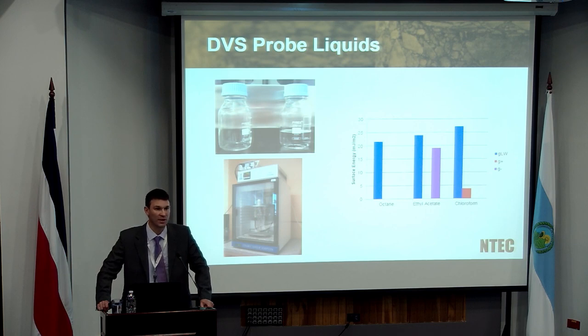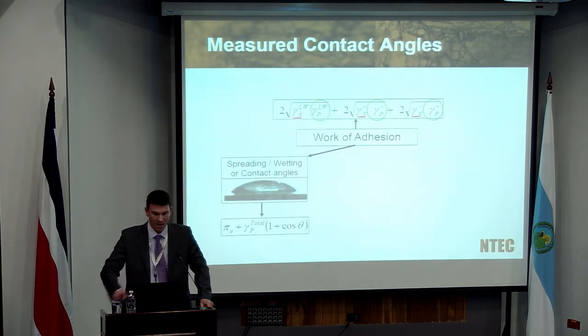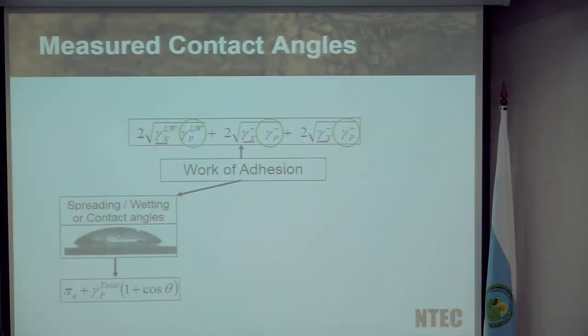How would we do it for the bitumen? Well, slightly different. Because now, although we're going to use exactly the same philosophy, we're going to use the approach that I explained earlier on, where you have effectively a material and you cover that material with a second material. And in terms of an aggregate, we say we completely covered it and therefore we had no contact angle. With bitumen, what we do is we take the bitumen and we do the testing at a low enough temperature so that bitumen is effectively almost a solid. And then we use probe liquids rather than probe gases to effectively see what the reaction is between a liquid and our pseudo-solid bitumen. Because bitumen would have a much lower surface energy than the aggregate, we don't get complete coverage. So we end up where we actually have to measure an angle.